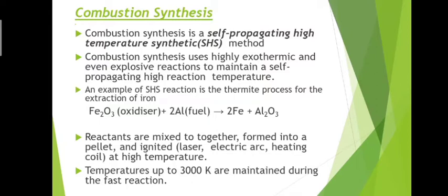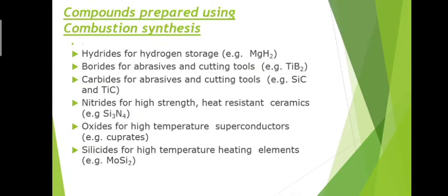Reactants are mixed together, formed into pellets and ignited at high temperature, and temperatures up to 3000 Kelvin are maintained during the reactions. Now the compounds prepared using combustion synthesis. We can prepare hydrides for hydrogen storage, borides for abrasive and cutting tools like TiB2, carbides for abrasive and cutting tools, nitrides for high strength heat resistant ceramics, oxides for high temperature superconductors, and silicides for high temperature heating elements.